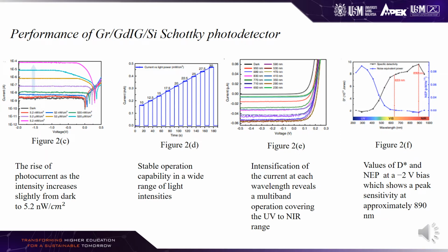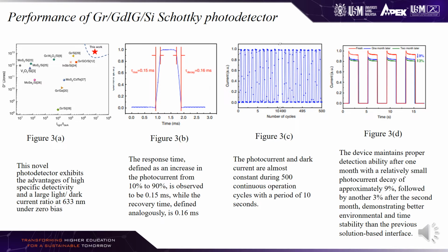Values of detectivity and noise equivalent power at a negative 2-volt bias show a peak sensitivity at approximately 890 nanometers, as shown in figure 2f. Next, figure 3a shows that this novel photodetector exhibits the advantage of high specific detectivity and a large light to dark current ratio at 633 nanometers under zero bias.